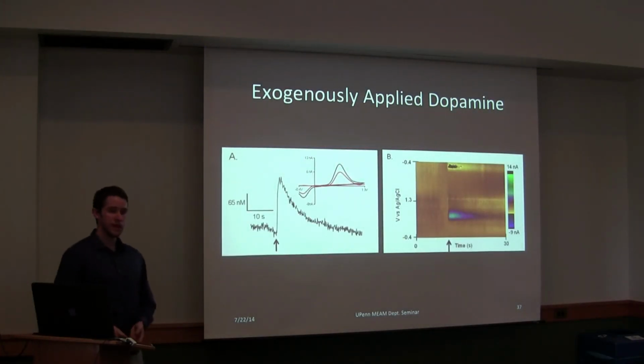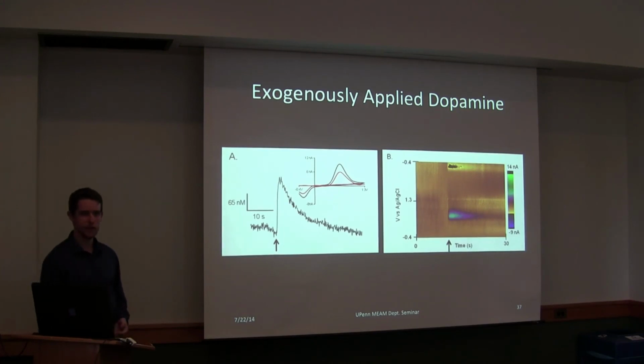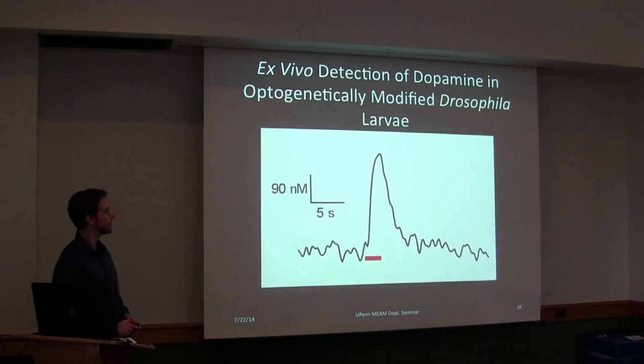And so with that, they moved to actual studies in flies. Here they use exogenously applied dopamine. They stick a carbon nanopipette into a larval ventral nerve cord, and then, using a separate pipette, apply dopamine. Why this is interesting is because you can measure how fast the dopamine gets taken up by the flies. Typically when neurotransmitters are released from neurons, the dopamine that is now in the extracellular solution gets reuptaken by these cells, so you can look at the uptake dynamics of the dopamine. If you didn't have the cells there to take up the dopamine, this fast scan cyclic voltammogram would have a continuous streak across this way. So we can look at those kinds of dynamics.